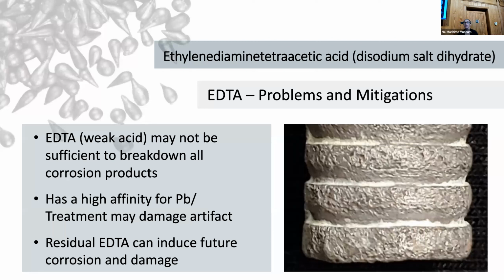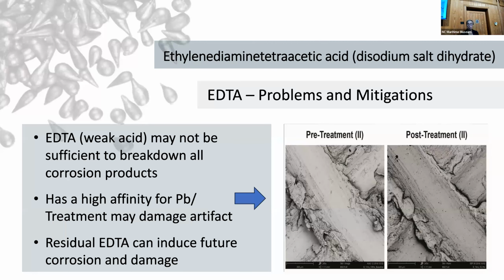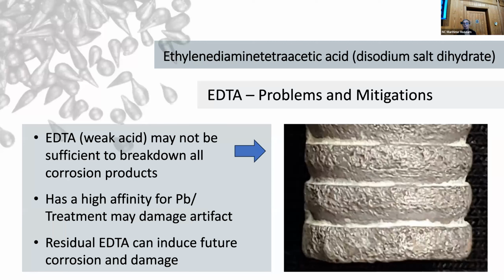And EDTA, especially because it is an acid, if you don't thoroughly remove it from the surface, it can induce future corrosion and damage the artifact, as we've discussed with those atmospheric acid attacks from organic acids in our display environment. Yeah. So these are just examples of, you can see there's still a little bit of corrosion product in those grooves that the EDTA was just not able to remove.